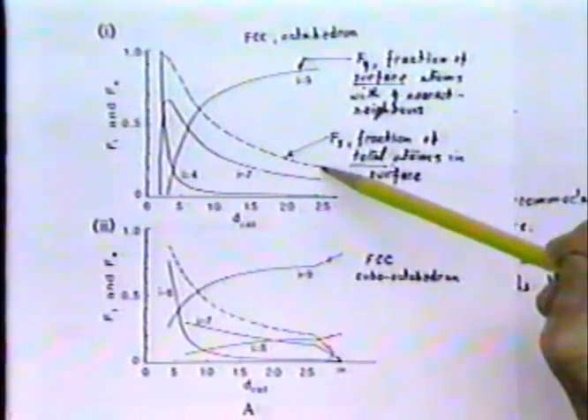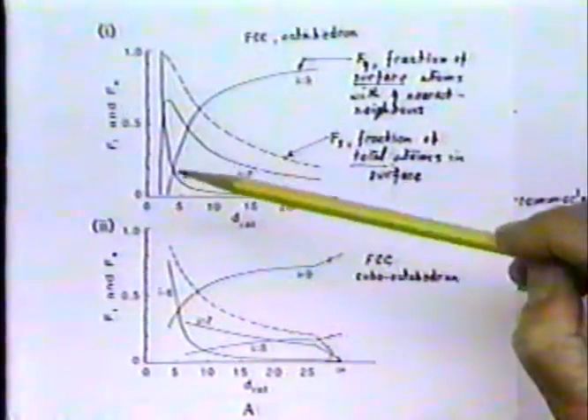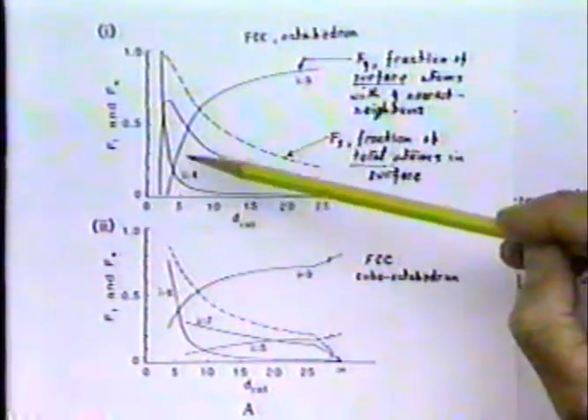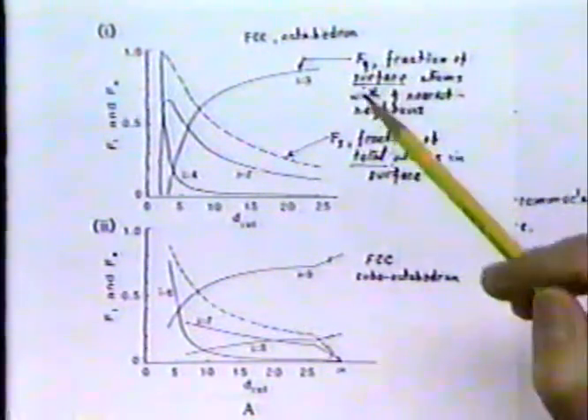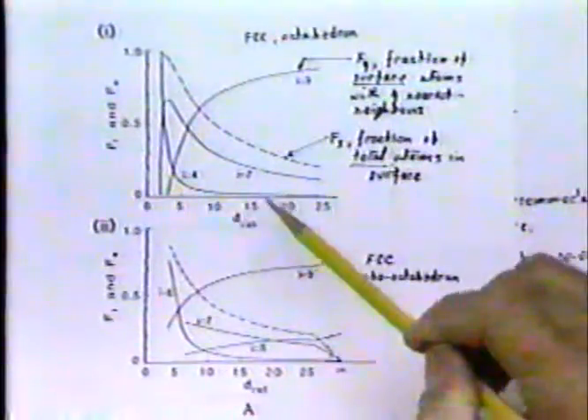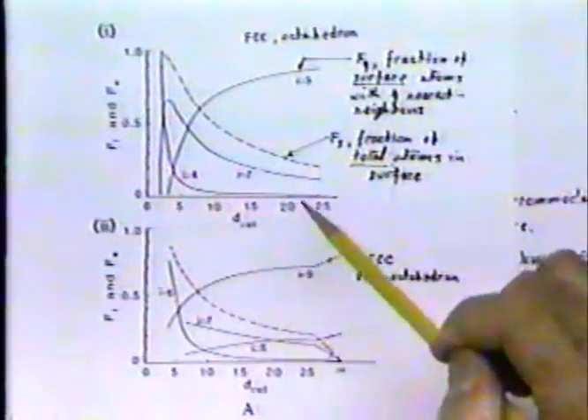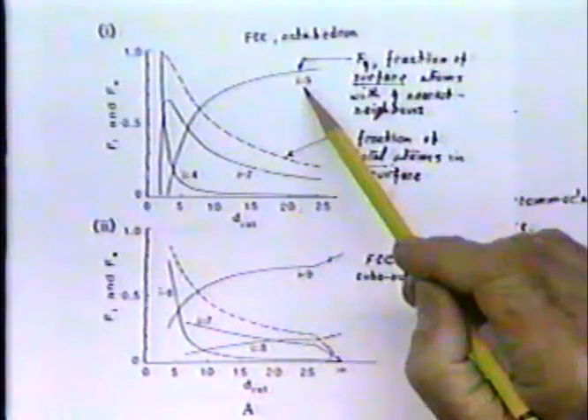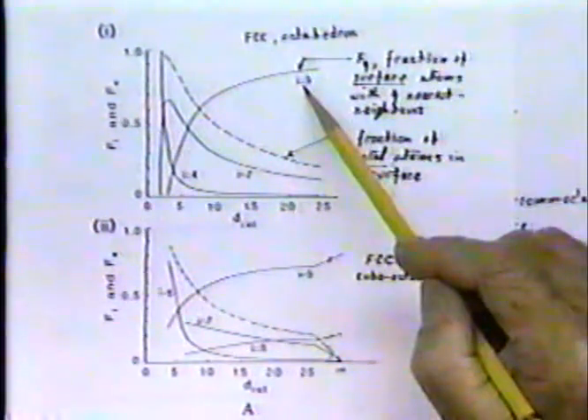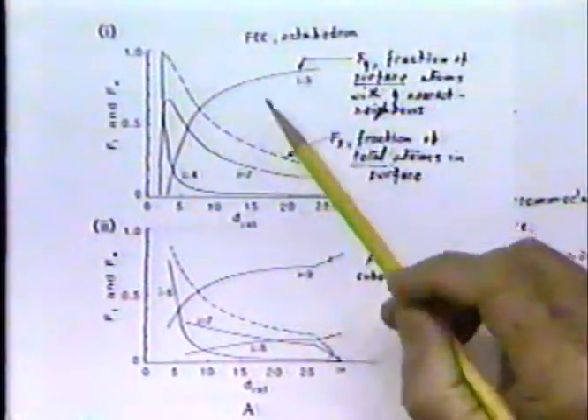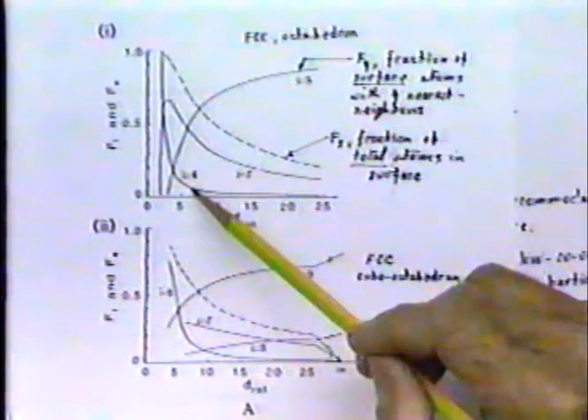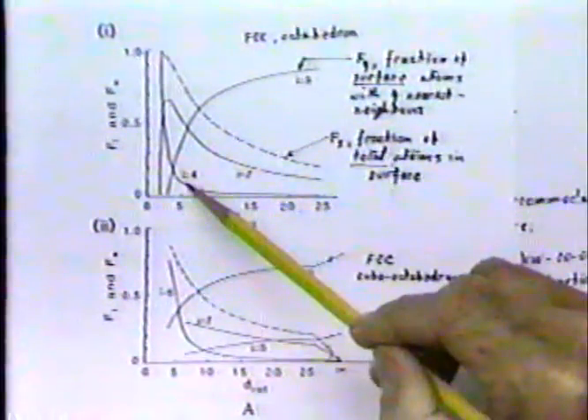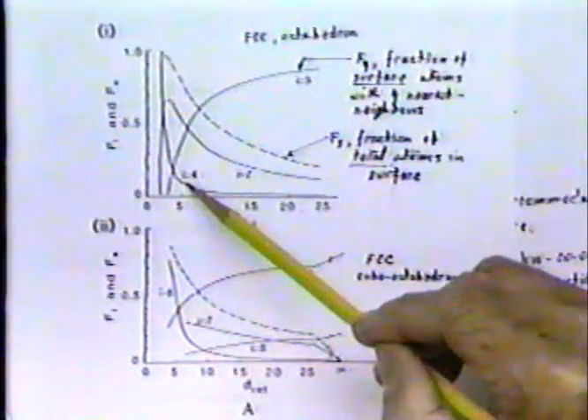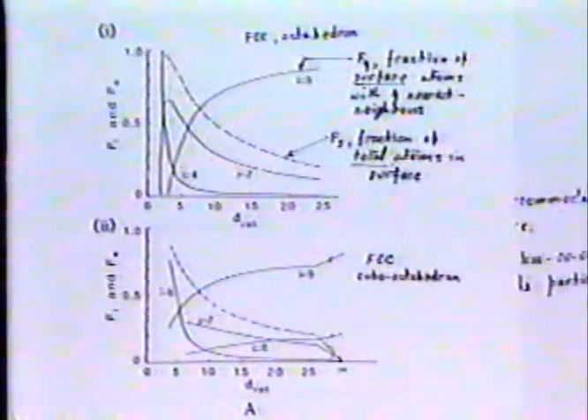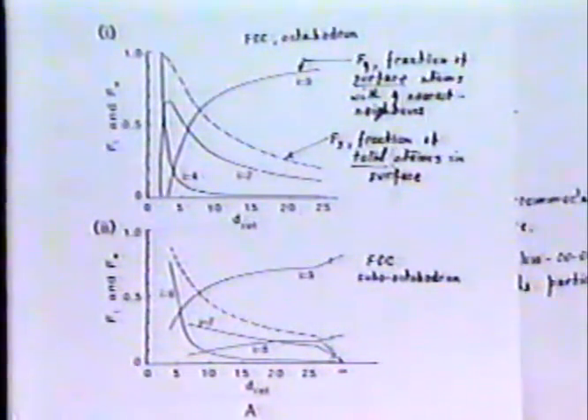And then also the fraction of surface atoms with various degrees of coordination also changes fairly rapidly over this relatively small size change. The curve I equals 9 refers to atoms sitting in a 1-1-1 face, and I equals 7 and I equals 4 are defined in the diagram for the octahedral crystal that's in one of the previous sheets. And the second diagram simply is the same sort of thing for the cubo-octahedral shape.